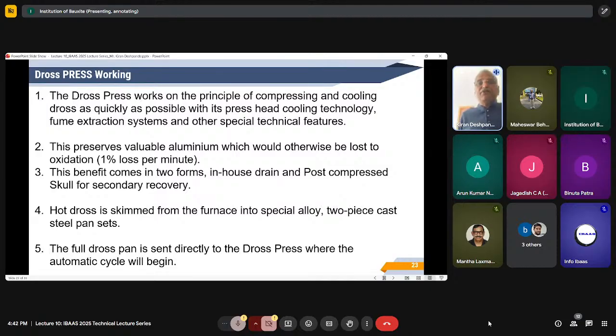So the DROSS press works on the principle of compressing and cooling the DROSS as quickly as possible with its press head cooling technology. The head which is pressing has a cooling technology, so it cools itself and becomes like a heat sink. It absorbs the heat from the DROSS. So your thermiting of the DROSS reduces, and evaporation of aluminium, converting into aluminum oxide or due to thermiting into the vapors, is greatly reduced. This preserves valuable aluminum which would otherwise be lost to oxidation. So the loss is 1% of the DROSS you are losing as an oxide. Once you create an oxide, you have further processing required.